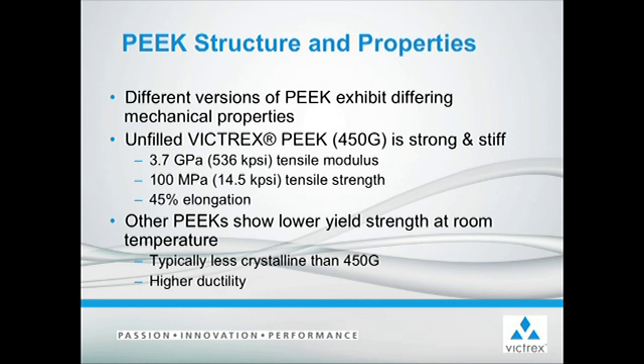The different versions of PEEK available on the market will exhibit different mechanical properties. For example, our VICTREX PEEK 450G, our unfilled general purpose grade, is strong and stiff. It has high tensile modulus, a high tensile yield strength, as well as a high elongation. Other PEEKs show lower yield strength at room temperature due to their lower crystallinity than 450G. However, this does relate to a higher ductility.